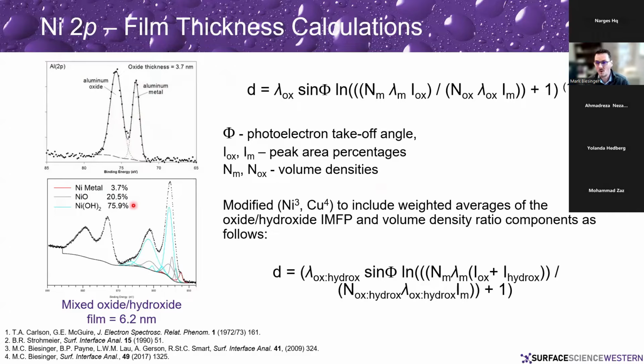But if you have a mixed overlayer, the inelastic mean free path for nickel oxide is different from the inelastic mean free path of nickel hydroxide. And so what we've done is we've used weighted values here where we plug all this data into this system, and this gives us an improved calculation of the thicknesses. In this case, we have so much oxide, so much hydroxide, and a little bit of nickel metal showing through, and we get a film thickness of 6.2 nanometers.